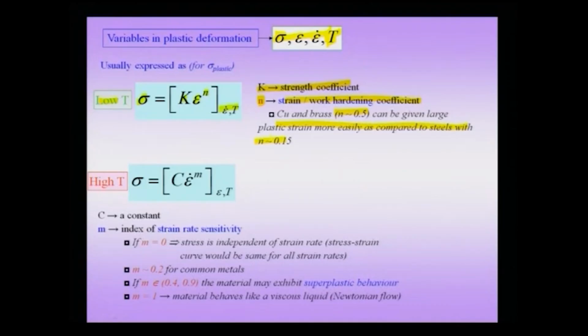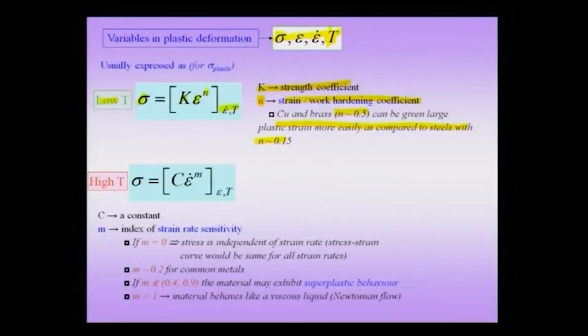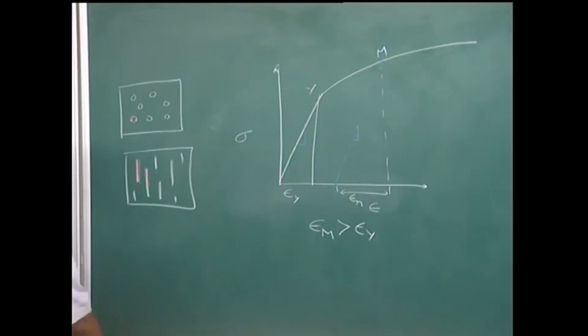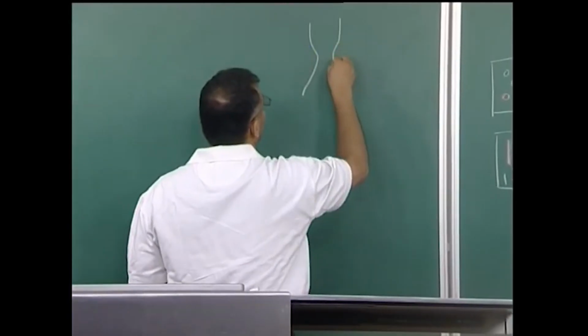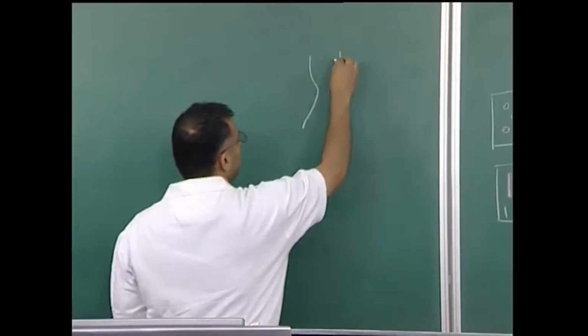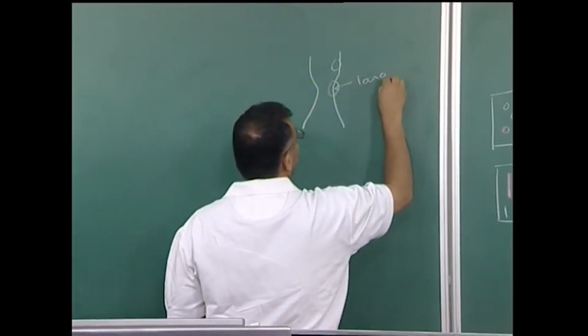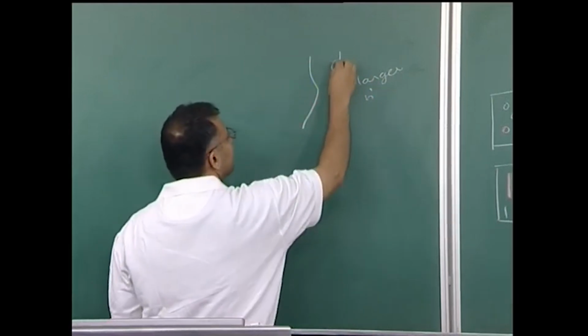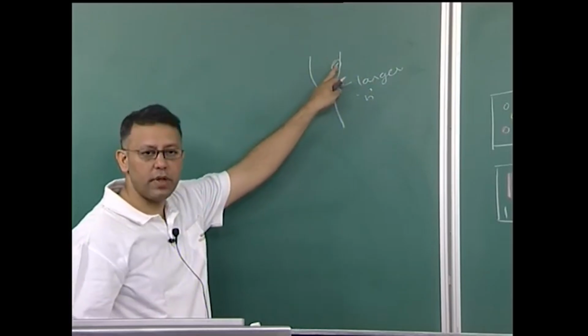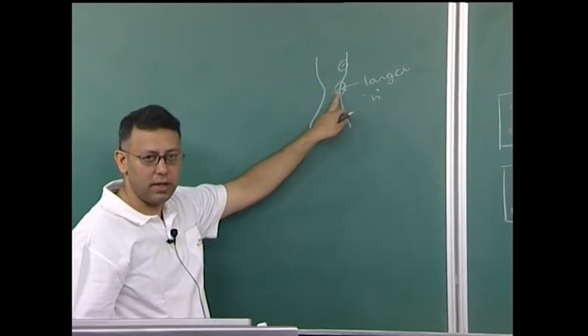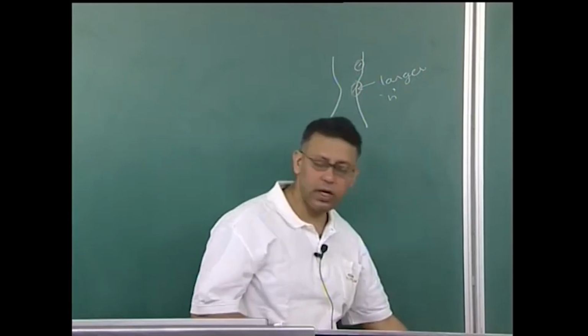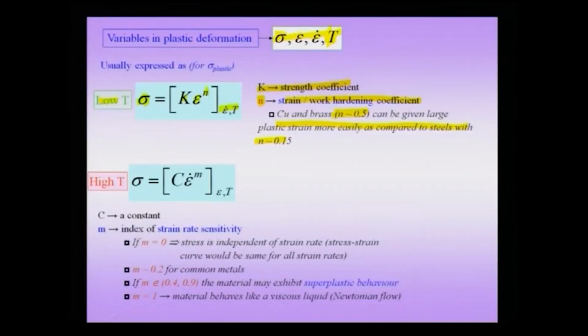Now, what is the importance of the strain hardening exponent? If there is a localized deformation like necking, then the strain there is larger, and because this n sits in the exponent, the stress is going to be larger there for further plastic deformation. This implies that the material adjacent to the region where you put more strain, which became harder, is softer. To draw schematically, suppose I had a material like this with a neck. This region has undergone more plastic deformation as compared to this region, and with a larger n, this material will be harder as compared to this region of the material. Because this region is softer, the plastic deformation will tend to spread here rather than get localized here. Therefore, I will get more tensile elongation if I have a larger n. That is why a material like brass with a higher strain hardening exponent like 0.5 gives you more plastic strain in uniaxial tension as compared to steels with a lower strain hardening exponent.